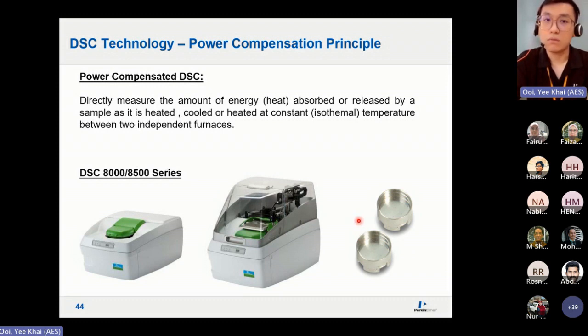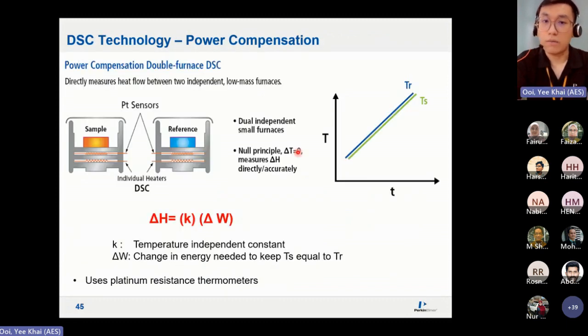So the difference between heat flux and power compensation is based on the null principle. Now delta T is 0. What happens here is, these two are your furnaces. Under them there are sensors, and there are individual heaters. As we heat up, at a certain temperature your sample will start to drift due to reactions or phase transitions undertaken. Then it will go back. But when it starts to drift, the sensors under the sample start to match with the reference. When there is 10 to the power of -6 delta T, the sensors give signals to the heaters, whether to supply or to withdraw energy to maintain the same temperature. This is why delta T is 0. We call it the null principle.